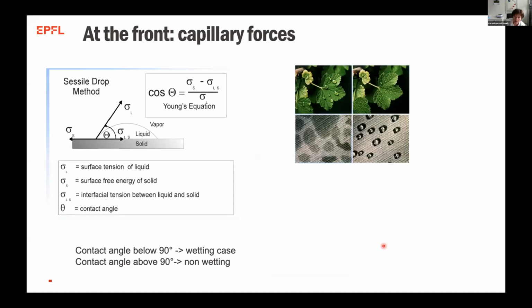So what's happening physically, you all have heard, I suspect, about Young's equation. If you put a drop of a liquid, which in our case would be the polymer, the resin, on a solid, which could be the fiber, you will have the formation of a droplet, with a contact angle. There are some equations that allow you to find what this contact angle should be as a function of the surface tension of the solid, the surface tension of the liquid, and the surface tension at the solid-liquid interface. Basically, you have a wetting case if the contact angle is below 90 degrees. What it means is that in that case, it's more favorable for the liquid to spread on the solid than for the vapor phase to stay.